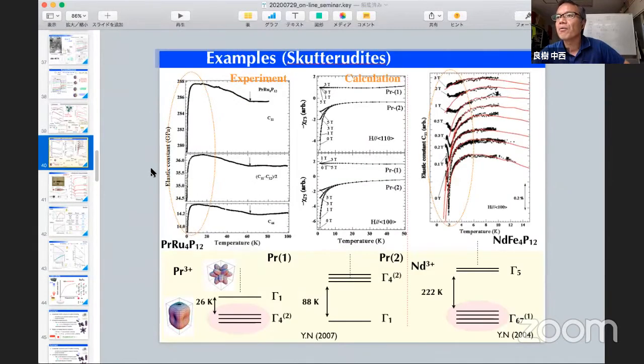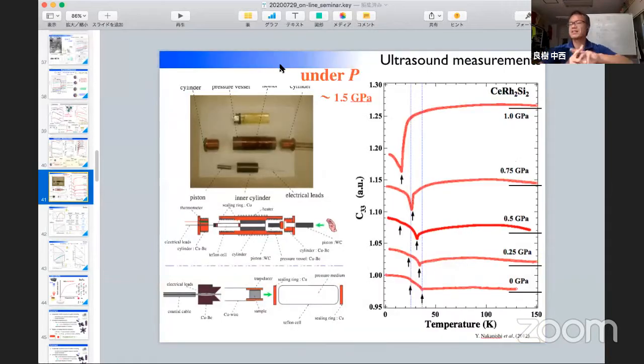Okay, so we also observe it in other systems containing other rare earth elements such as praseodymium and neodymium. As you can see, the pronounced elastic softening, highlighted here, is observed in the temperature dependence of the elastic constant. So this is quite different behavior compared to ordinary, normal materials. Not only at low temperature, but also with other physical parameters such as pressure, we could find this kind of behavior. This is one of the recent featured topics of our research.